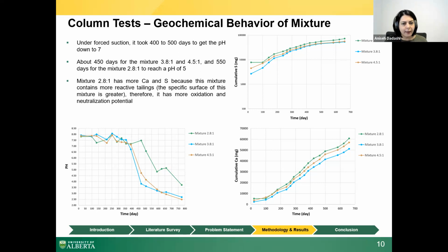It took even more for the mixture of 2.8 to 1 to reach a pH below 5 because this mixture had more tailings, and more tailings means more calcium and sulfur, which means more oxidation and neutralization potential. Also, for this mixture with more tailings, water content is higher, which leads to low diffusion, which makes this mixture more chemically stable, because this mixture limits the oxygen flow.